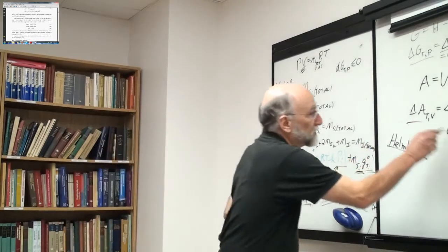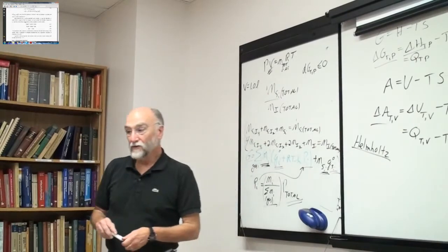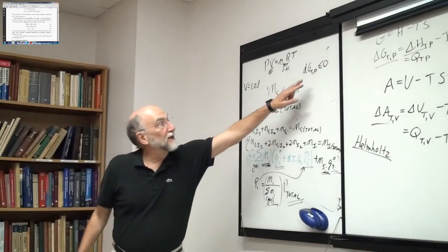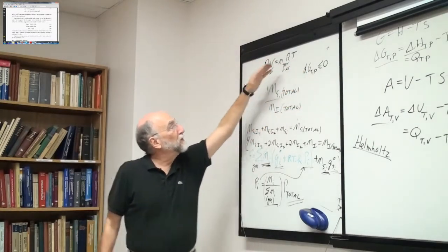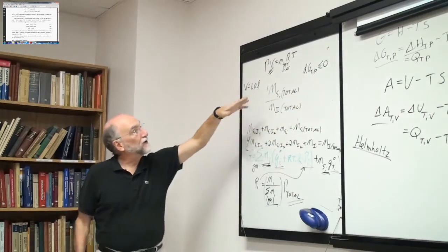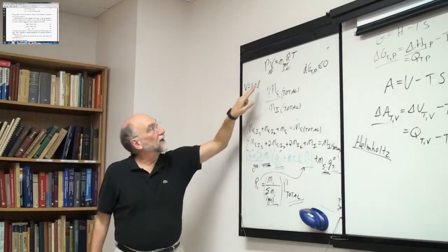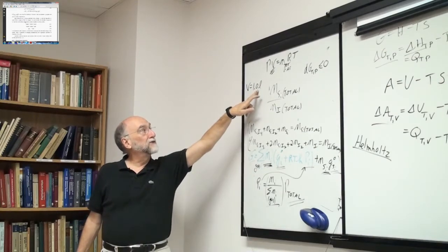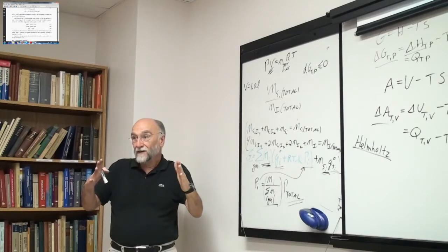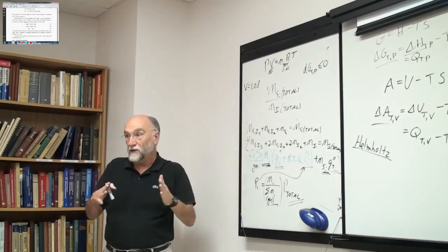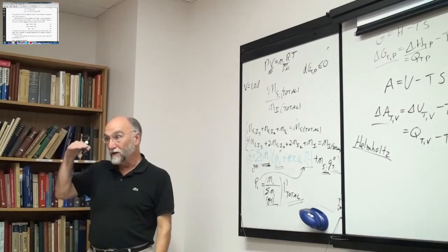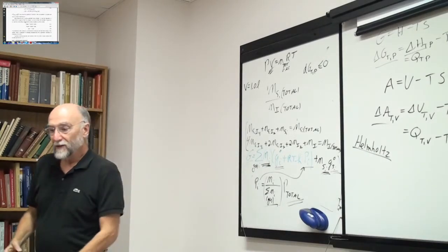So we can write all this kind of stuff, but it isn't really all that terribly useful because that's not the way our algorithms really work. The algorithms really guess the temperature and pressure. How do we know whether to go up or down? I guess a pressure of 1 atmosphere, I let the thing reach equilibrium, then I calculate the volume. If the volume's now too big, then the pressure has to be higher. If it's too small, the pressure's already too high and has to be reduced. So you do it incrementally until you narrow in on the final answer. That's how you do it.